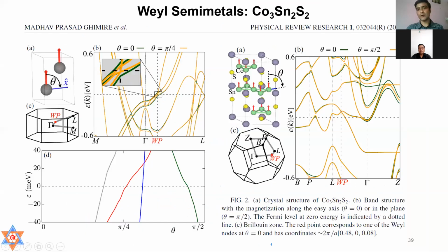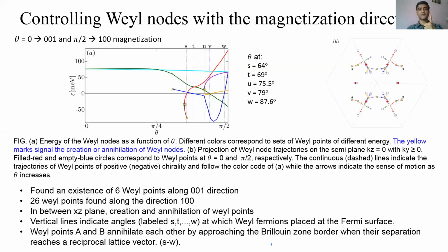And we consider a magnetic rotation. Yes, two minutes, please. When we say magnetic rotation, we align the direction of the spins first along one of the easy axes, which we call the C axis, and then we apply a magnetic field to rotate the spins along different directions, and we end up on another plane, that is in-plane, which is called the 100 direction. Here, theta equal to 0 corresponds to the C axis, and pi by 2 corresponds to the 100 magnetization. So we rotate the magnetization in this way.